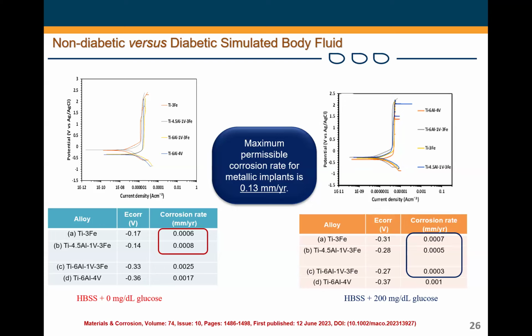And when you now go to our own alloys, the ones we really love, which have partial replacement of vanadium with iron, you would see that even after 220 seconds, we still have higher thickness of titanium oxide, because here again, the color coding is different, but I intentionally present the raw results without having to replot them. So you see that we have higher thickness of titanium oxide in that case, and we could observe the same trend. It does seem to me that maybe it's not a bad idea to add iron to titanium, because many are of the opinion that adding iron to titanium is never a good idea. If you do partial replacement, you stand a chance of improving corrosion and mechanical properties.